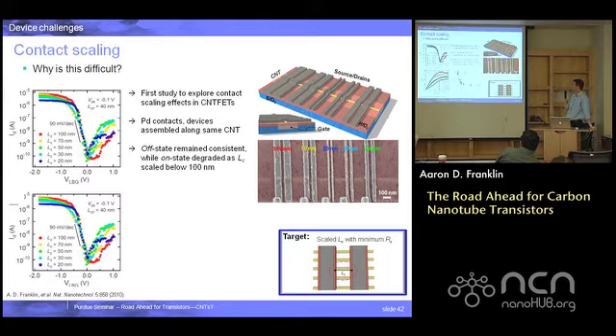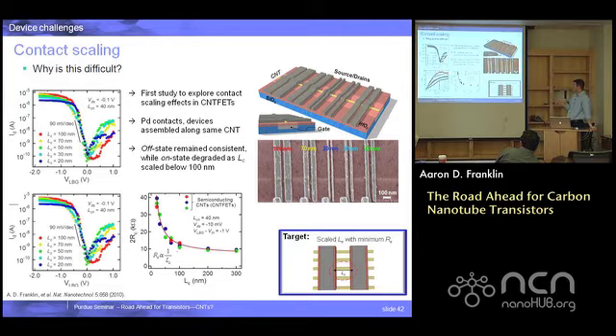And this is the result, the most important one in the bottom middle here, which plots contact resistance versus contact length. And you can see that below 100 nanometers, you see a dramatic increase, about a 1/LC relation in that contact resistance. And this is not to say, oh, well, great, a hidden huge problem with nanotubes. It's never going to make them work. Whether it ever keeps them from working or not is an unknown, but it's not unique to nanotubes. Any type of transistor, including the standard MOSFETs throughout the ages, have the same type of trend. In fact, it has a similar 1/LC dependence. But the physics are entirely different. What I get out of a 3D to 3D silicide type of contact in a MOSFET is very different from a 3D to 1D contact to a little carbon nanotube, where you have Schottky barrier and other issues that are likely playing a role. So there's so much work that could still be done to understand this, and hopefully, by understanding it, provide some improvement for this scaling trend.